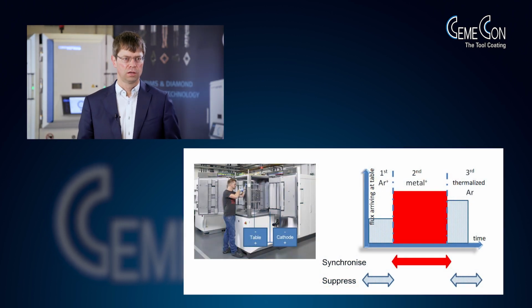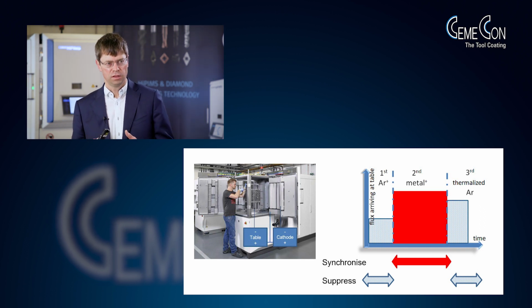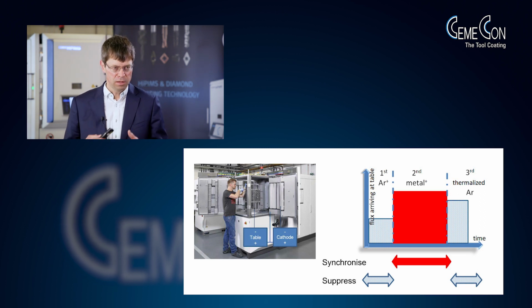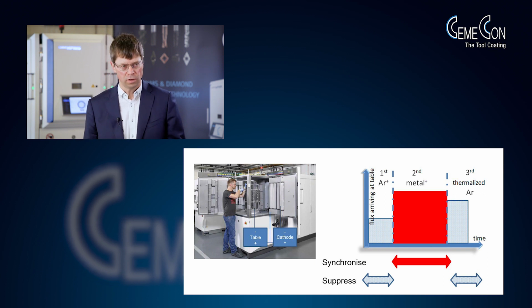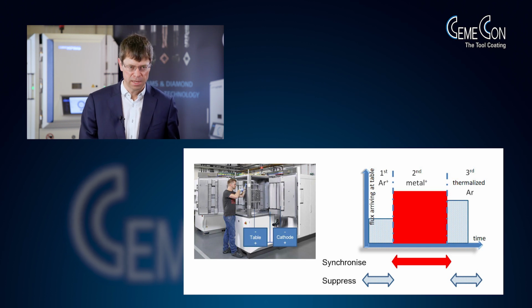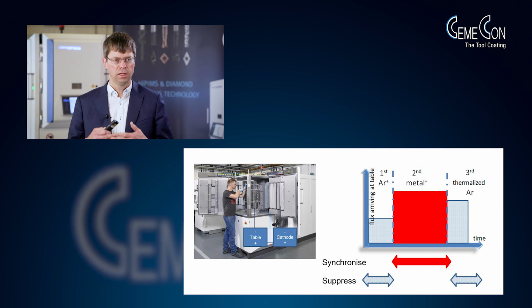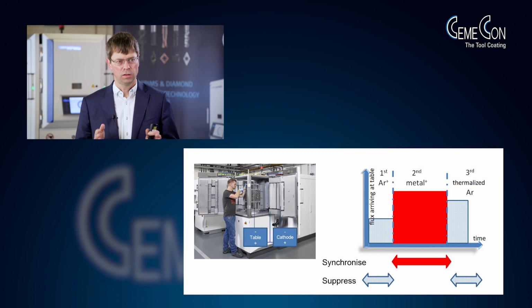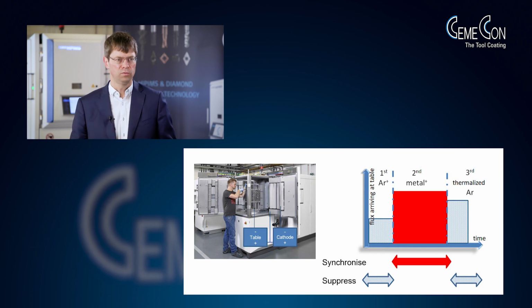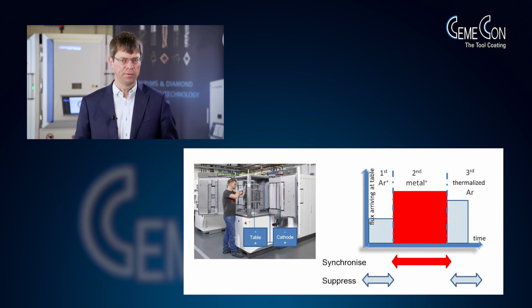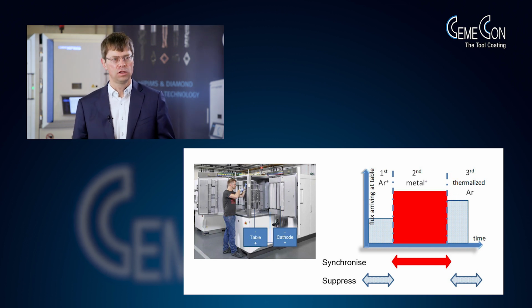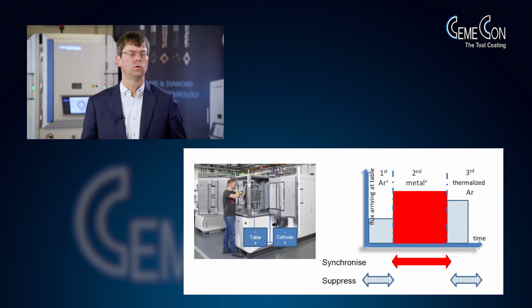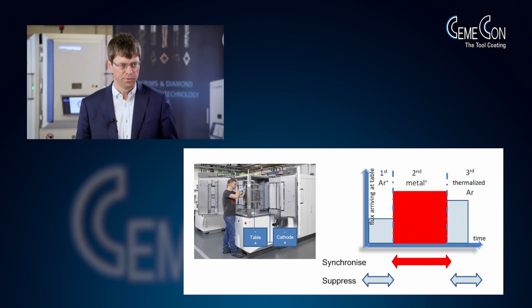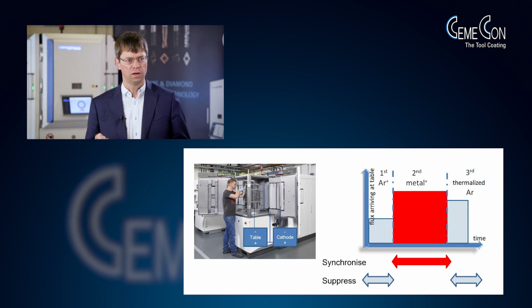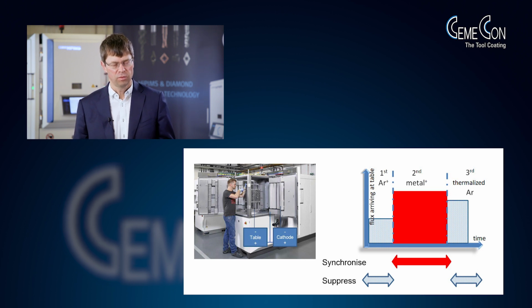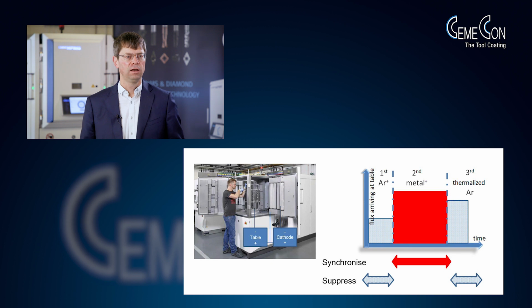The key technology step forward in HiPIMS is that we at CemeCon were not just looking into putting pulses on the cathode, but analyzing the process and synchronizing the pulses on the cathodes with what's going on at the bias table. On the bias is your tool placed and is receiving the material from the cathodes. From the cathode is coming during the pulse the metal from the target. That's of course what we want for making the coating. But on the other hand, there are in the plasma, just from the nature of the process, some unwanted additional species. These ones should not go into the coating grid because they distort the grid and they make the stress. And the thing in HiPIMS synchronization for selective ion biasing is attracting the metal coming from the target, that's what we want, and suppressing the unwanted parts.